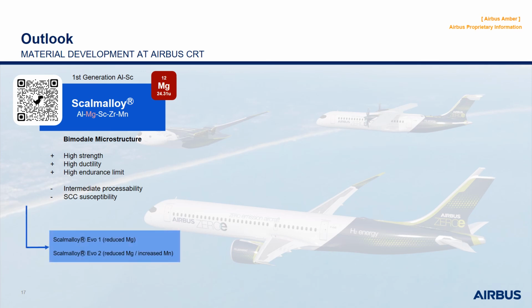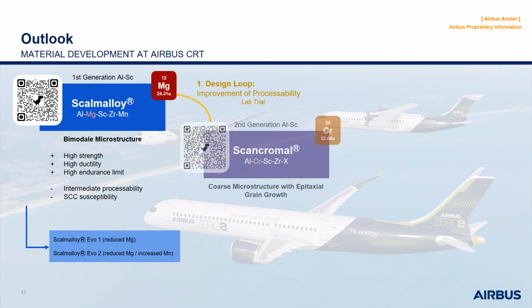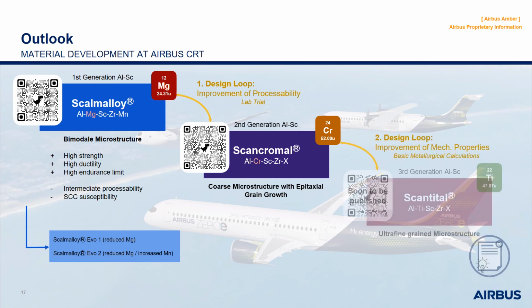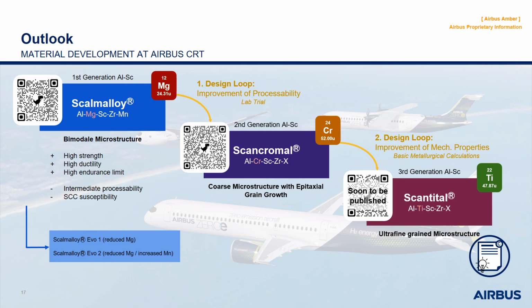Also, with the reduction of the magnesium level to a certain threshold value, we made big progress towards a stress corrosion resistant material. Nevertheless, we focus also on further developments in order to understand the microstructure evolution during the process as a function of the alloying composition. Therefore, we developed our second generation aluminum alloy for additive manufacturing, and in our second design loop, our third generation aluminum alloy for additive manufacturing. And with all those design loops, we focused on the replacement of magnesium and the microstructure tailoring. The very promising results of these developments will be published very soon.